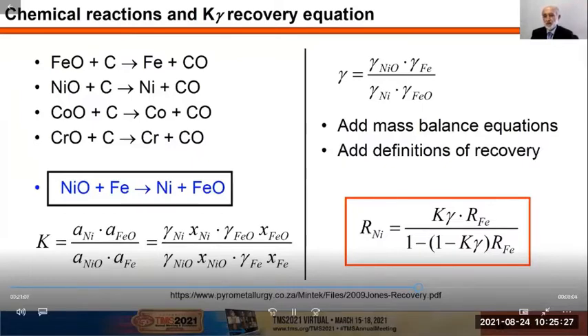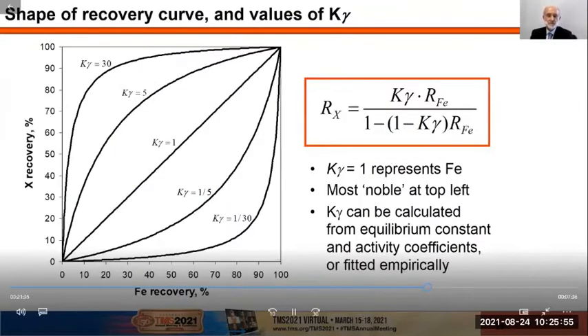We add mass balance equations and definitions of recovery for both the iron and for the nickel, and finally result in a relationship between the recovery of nickel as a function of the recovery of iron and this number K gamma, just purely a number, dimensionless. The derivation of the equations can be found in the reference at the bottom of the screen for those interested.